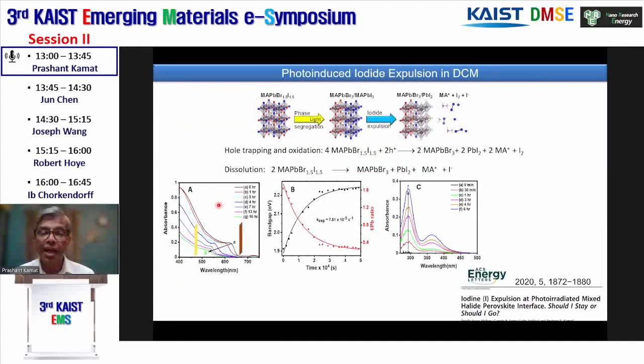Okay, then there is another aspect of it. If you take this halide film, again, you can see this movement of halide ions by doing a spectroscopy measurement. So we took this film, deposited on a glass slide, and shone light in the presence of DCM. In the dark, in DCM, this film is stable. But under light, what we see is a shift in the absorption peak, indicating the expulsion of iodide. We monitored the solution, and we can see the I3- coming out, forming in the solution. And what we see is, we see up to bromide, this one.